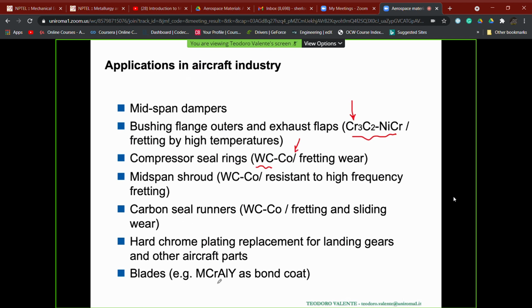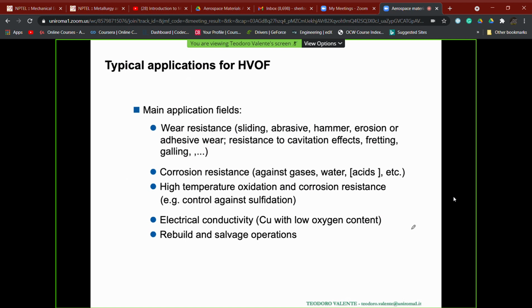etc., as reported here. Apart from, again, it must be mentioned, the MCrAlY coatings, which act as bond coat in thermal barrier coatings. We have also this area, which is very important and very interesting, for which we will have some dedicated slides, but let me anticipate the possibility to use this kind of technology with proper coatings in order to replace hard chrome plating, which is a very simple, very easy technology, but very dangerous for the safety of the operators. For example, for the surface functionalization on landing gears or other aircraft parts. So this is what we have said.